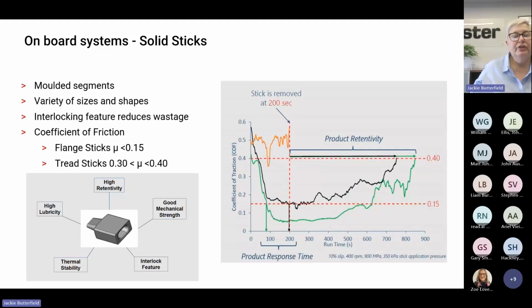And the coefficient of friction that they give is for flange sticks. So they will give a coefficient of friction of less than 0.15. And for the tread sticks, they will give an intermediate coefficient of friction between 0.3 and 0.4.